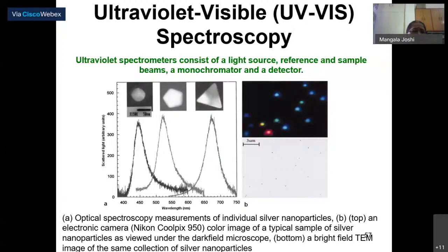Now you have our humble ultraviolet-visible spectroscopy technique, which we use in our chemistry lab to look at colors, chemistry and other things. It is a very, very useful technique because silver, gold and other nanoparticles show surface plasmon resonance in the color, and the color changes with the size and shape. So you can measure the dispersion of nanoparticles on a UV spectrum, and you can look at where the lambda max is. As you can see in this diagram, different shapes of the silver nanoparticles absorb at different wavelengths. That means they will show different colors. Next.